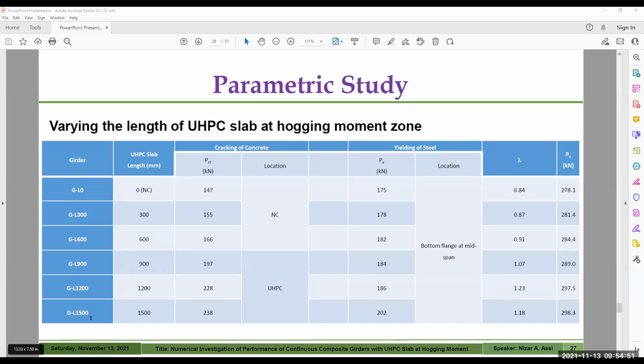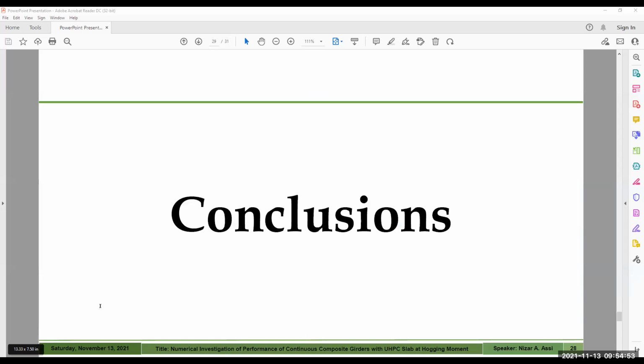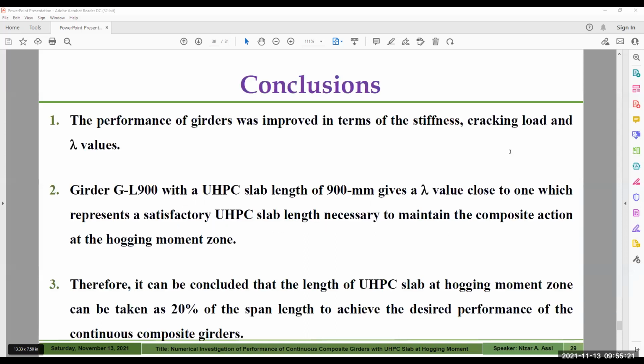The conclusions that can be drawn from this study, that the performance of girders was improved significantly in terms of the stiffness, cracking load, yielding load, and lambda values. The continuous girder with UHPC length of 900 millimeter gave a lambda value close to 1, which represents a satisfactory length necessary to maintain the composite action at the hogging moment zone.